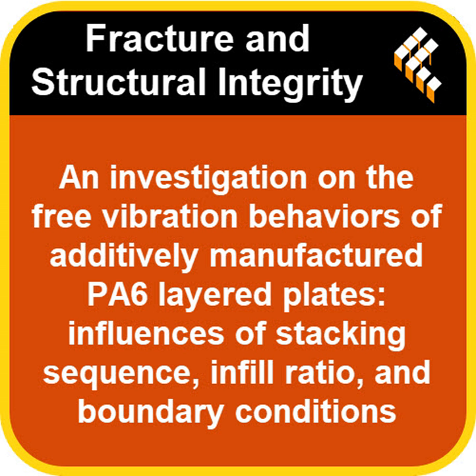And conversely, placing the dense 100% infill layer in the core with lighter 40% infill on the surfaces, a 40, 100, 40 setup. Yes. That generally resulted in the lowest natural frequencies. Whoa, okay, that feels completely counterintuitive. You'd naturally think packing more material, especially into the core, would make it stiffer and increase the frequency, or at least that the solid 100% one would be highest. What's the why behind this?